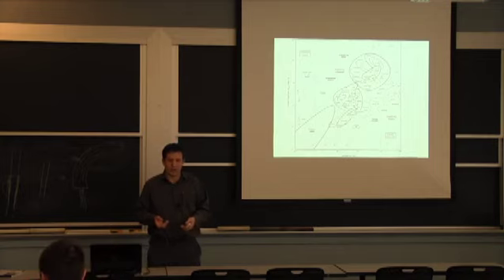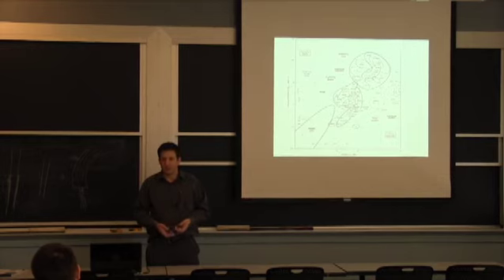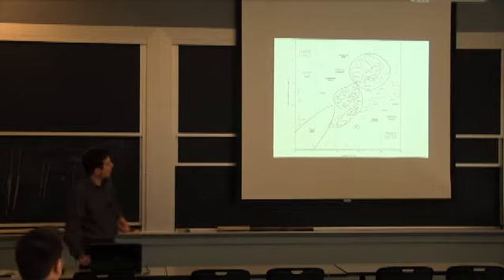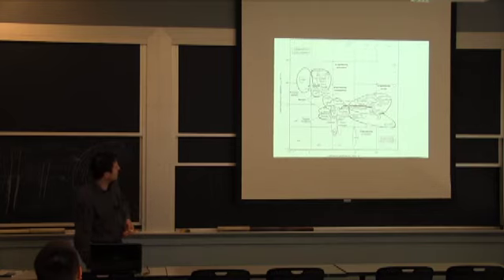But the cost aspect of that was to make a very thick wall, so the stresses are sufficiently low that the creep, the deformation that happens over time, is still negligible within a 25-year exposure cycle. So it just becomes a different requirement. It's strength. Strength relates to the viscoelastic as well. So if you think of a plastic as relatively high strength than another, most likely it will also have less viscoelasticity, less deformation over time. And we definitely can go through that.